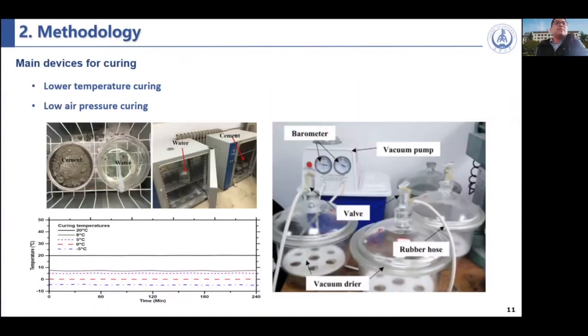For the main devices for curing, we use two kinds of curing. The first one is lower temperature curing. Before the mixing of the paste, we put the cement and the water at a fixed temperature that is the same as the curing chamber. The second curing, we developed a system to produce low air pressure. This is what we use in the laboratory to measure the paste. And we also have a bigger chamber to produce the lower air pressure so that we can cure the cement paste and the concrete samples.